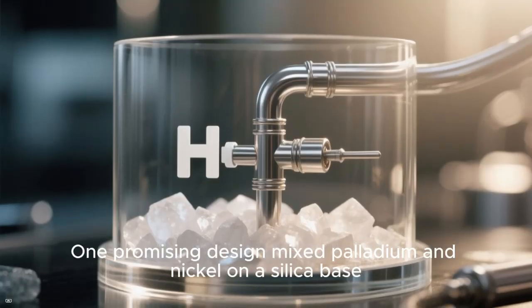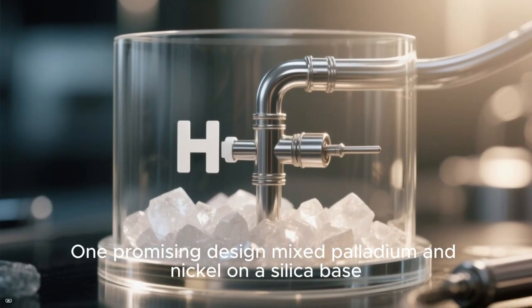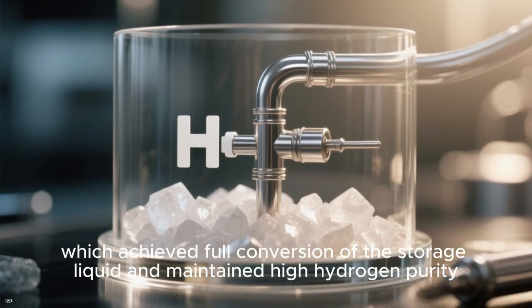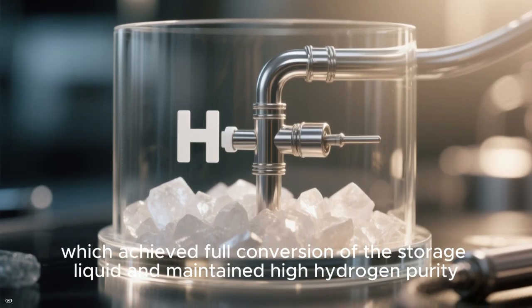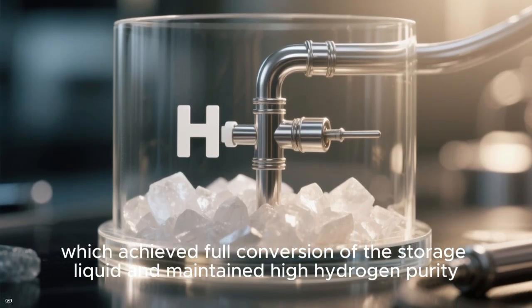One promising design mixed palladium and nickel on a silica base, which achieved full conversion of the storage liquid and maintained high hydrogen purity. This PdNi combination even outperformed the version that used only palladium, showing that smart combinations of metals can be more effective and less expensive.